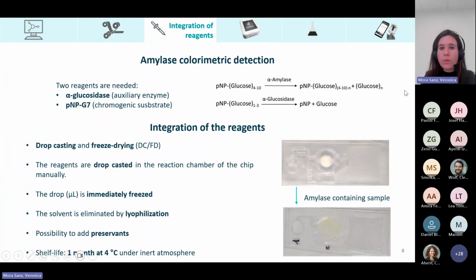Well, as I explained before, we are going to be measuring two enzymatic reactions, and for this we need to employ some enzymatic substrates. To simplify the handling and to reduce the user interaction, we introduce these reagents into the reaction chamber of the chip, and we employ different methods. Here, for amylase, we need to employ two different reagents, an auxiliary enzyme, alpha-glucosidase, and the chromogenic substrate, pNP-G7. By the action of both enzymes, this compound, pNP, is released, and we can measure the absorbance at 405 nanometers.